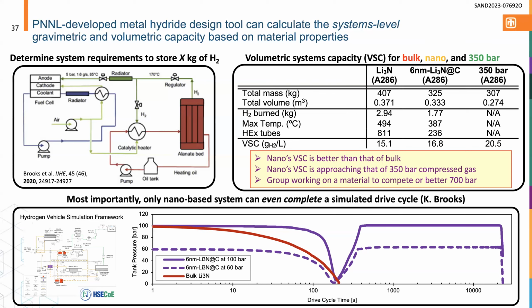So in solid purple there is the nanoscaled material, and it's the tank pressure as a function of drive cycle time. So that rapid decrease around 100 seconds is coming from the fact that you have to burn a lot of hydrogen to heat the material up so that it can release more hydrogen. But it is able to do that and then continue on its way and finish the drive cycle.